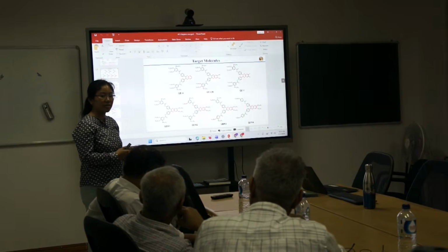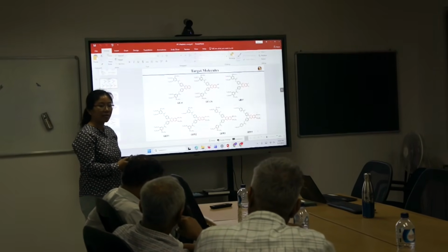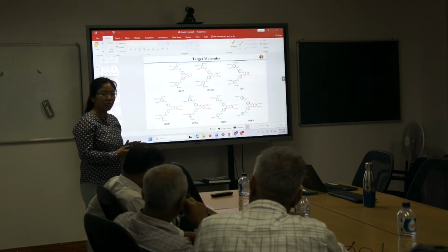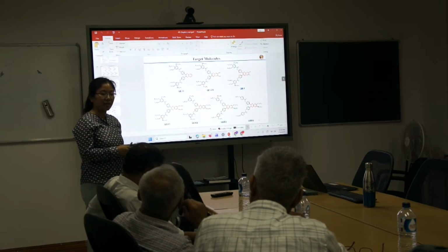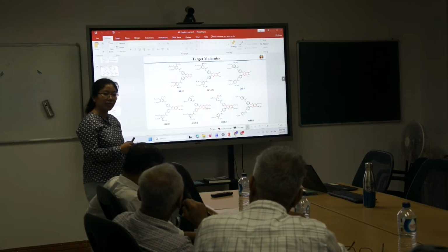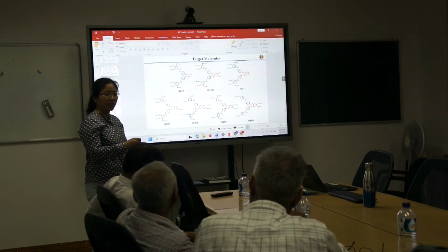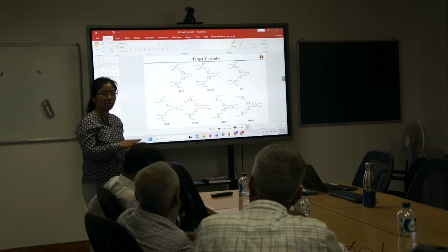First we check by polarizing optical microscope, and we heat it to its isotropic temperature, and then cool it slowly at a slow rate, and observe under the microscope if we find the formation of birefringence and texture. That is a preliminary study. If it forms texture, we check for the shearability of the compound. Liquid crystalline molecules are known to show shearability.